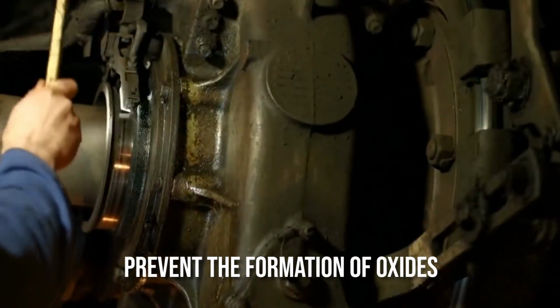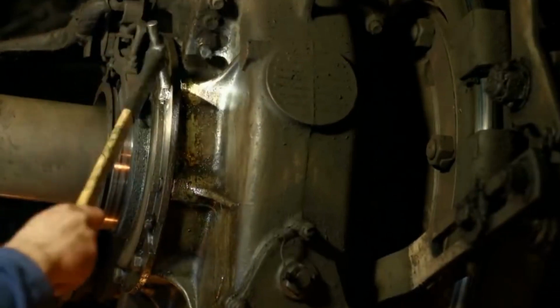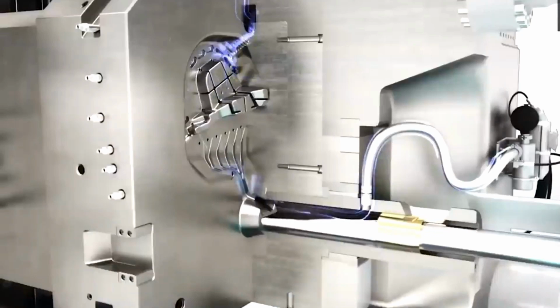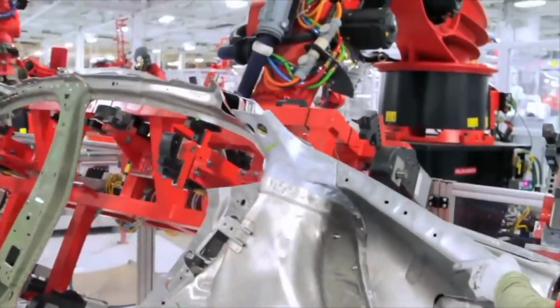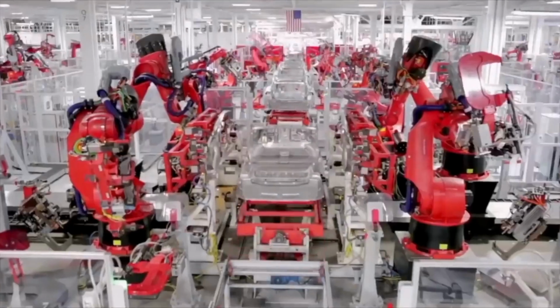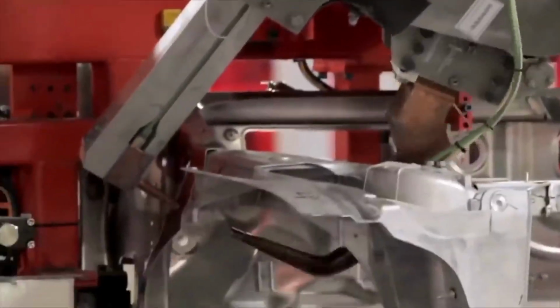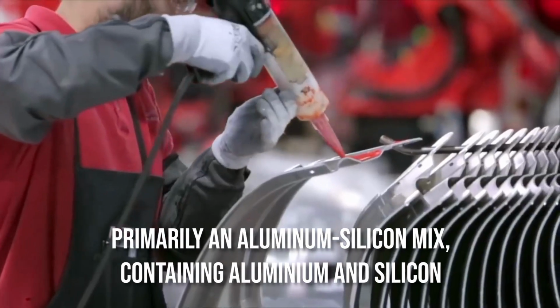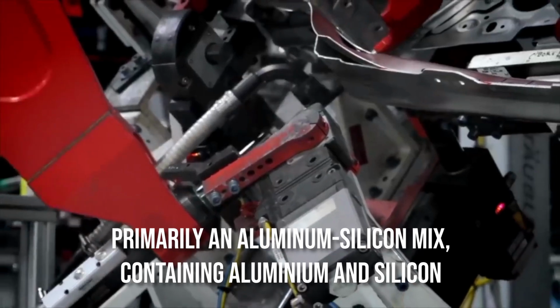Before being laser trimmed, drilled for fittings, and computer measured for accuracy, the remaining useful part of the casting is X-rayed to check the internal structure. According to reports, the cast aluminum alloy used in the large Tesla chassis parts is primarily an aluminum-silicon mix, containing aluminum and silicon as well as a number of other trace elements.